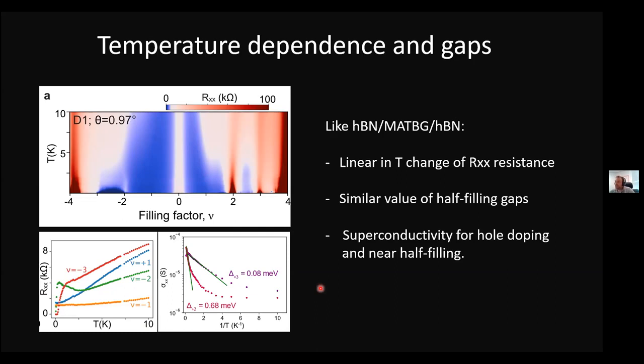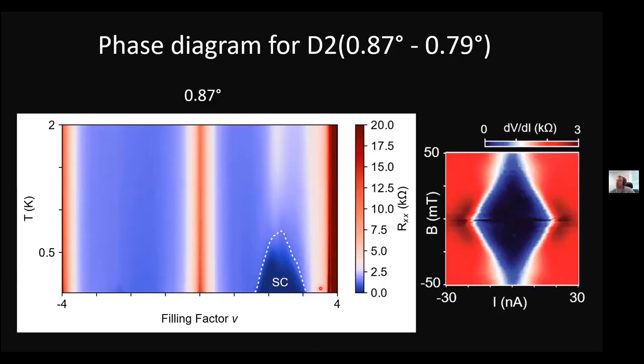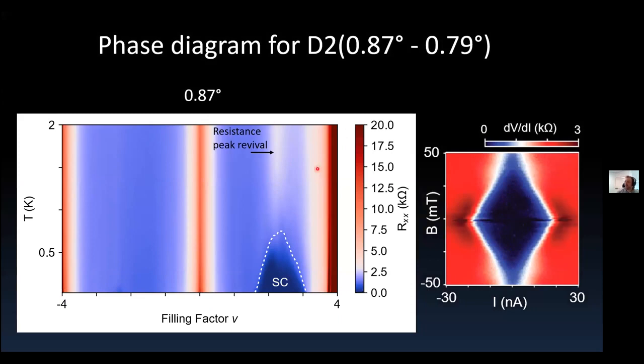So the interesting part is what happens as you now decrease the angle. And this is a second device. This angle is 0.87 degrees. And already here you can see you still have the peak at charge neutrality. You have insulating gaps at full filling, but now there's practically not much left of the correlated insulating states. There is some resistance peak here. I mean, this is still superconducting, and there is a revival of the resistance peak, and this maybe relates to something that Andrea mentioned yesterday.